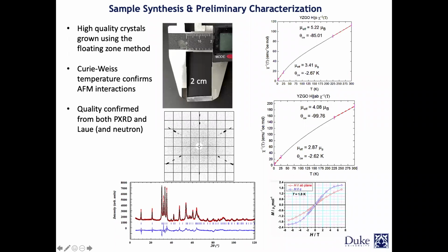This is the powder pattern for it. The data is shown in red, and in black you're seeing the model. So it shows that there is no impurity, and the model fits very well with the data.